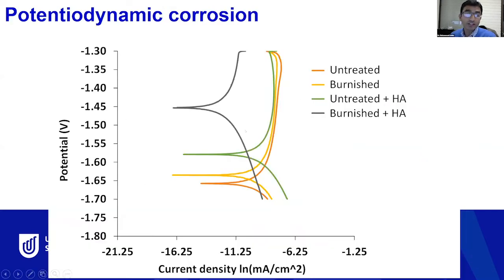So these are the corrosion results. I would like to highlight them mainly because these are the main results. We can see that, compared to the untreated surface, by applying the hybrid modification, which is the burnish plus HA coating, the corrosion potential has been shifted to the positive. So the corrosion potential has increased, and we can also see that the corrosion current density has been lowered. As you can see, the shift of this line from the bottom to top means that a higher corrosion potential is better in terms of corrosion resistance.